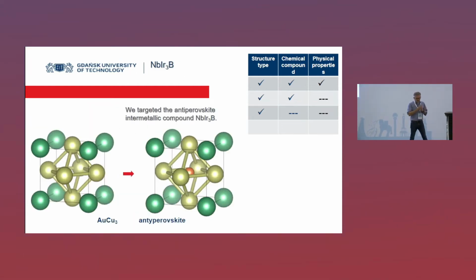Now, I smoothly go to the titled compound, and still, this is the same strategy. So the structure type is known, but we want to do something else. So niobium iridium 3 boron, the gold copper 3 crystal structure type, this compound has been studied. There is no superconductivity, fine, and we ask ourselves, is it possible to put a small atom like boron inside this octahedra?